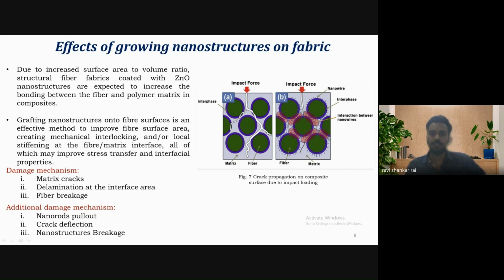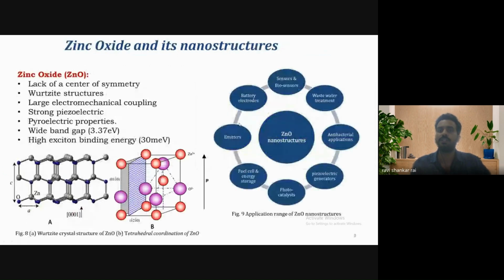After that, there was another mechanism that was found. If there is no nanostructure, there are chances of three damage mechanisms: matrix crack, delamination, and fiber breakage. But due to the addition of the ZnO nanostructure, there are additional damage mechanisms, that is nanorod pull-out, crack deflection, and nanostructure breakage. So overall, the load transfer capacity and stress resistance capacity will be improved.